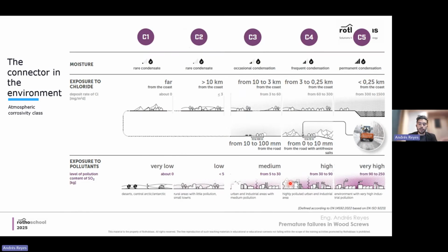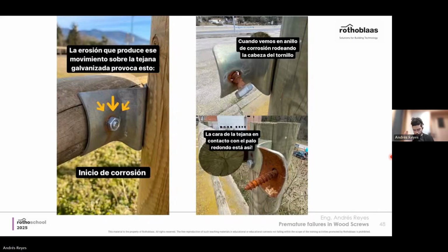Corrosion classes of atmospheric exposure are defined more or less from the distance to the coast, salts being the most important agent for atmospheric corrosion. Not the only one. For example, sulfites can also lead to corrosion if you are close to industrial environments. But the most important, at least for residential, is definitely the distance from the sea. So this is a thing that needs to be considered when choosing the material and knowing the corrosion risks.